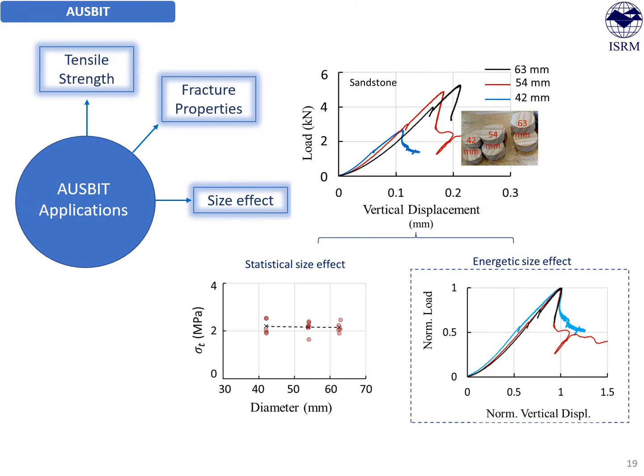However, the energetic size effect cannot be captured or assessed via the conventional approach. However, thanks to AUSBIT, we can now analyze that as well. The energetic size effect is the effect of specimen size on the post-peak snapback behavior of the disk specimen. So as we keep increasing the size of the disk specimen, we expect a relatively higher magnitude of snapback response, because as we increase the disk specimen size, the volume